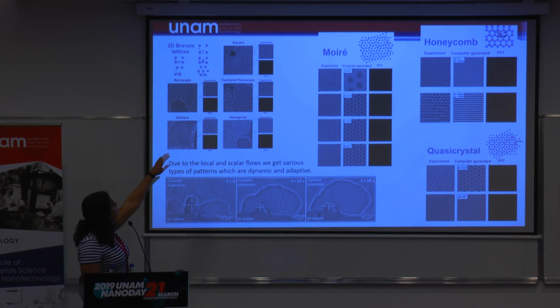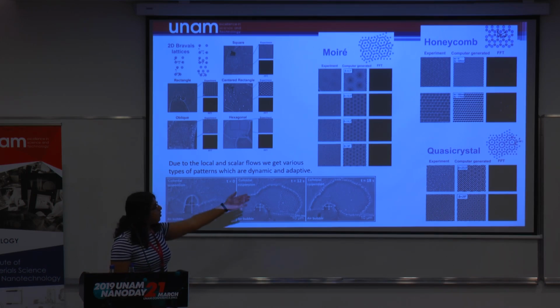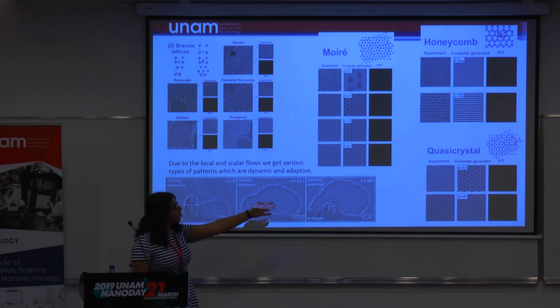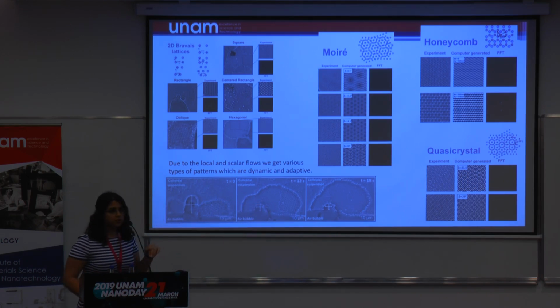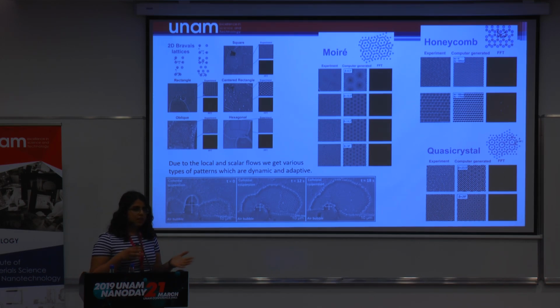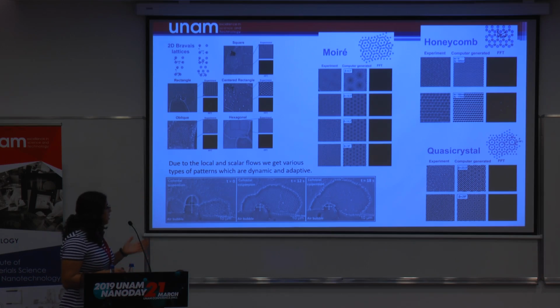Here you can see all the 2D Bravais lattices. We use Fourier transform analysis to identify our patterns. And also we observed moire patterns and quasi-crystals which are created from two layers of hexagonal lattices rotated on top of each other, and also honeycomb lattices which are created from two hexagonal layers shifted on top of each other.